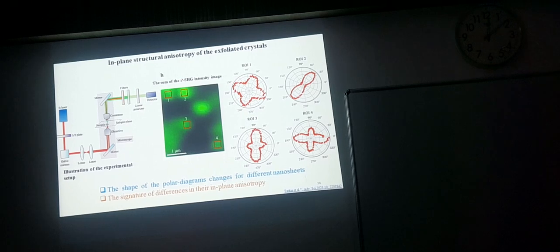In this case, we use a microscopic technique which was developed in the center. This is polarized second harmonic generation. What we did here, actually, is scan a certain domain of the sample where multiple flakes are situated in different directions.